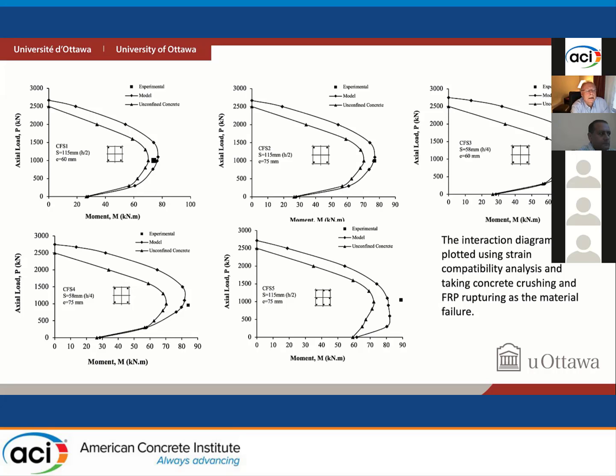And the confined concrete model was used to generate confined interaction diagrams, in which case the crushing of concrete was taken from the moment curvature relationship as the maximum crushing point on the interaction diagram, rather than assuming a strain value. Whereas for unconfined concrete interaction diagrams, we basically used epsilon CC of 0.0035 as per the Canadian standard.